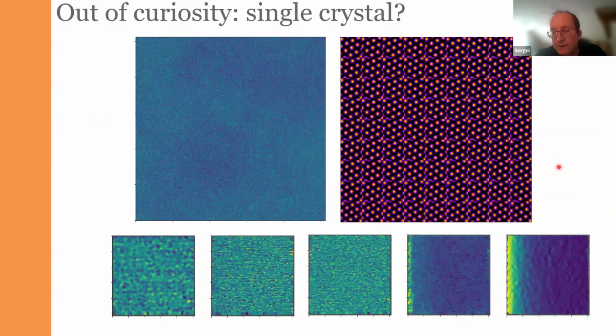Now, another very interesting thing that autoencoders allow us to do is that they give almost impossibly precise information about the uncontrollable factors of variation inside the material. What I mean by that is, if I take interesting looking images, meaning multiple phases, defects, whatever, VAEs are going to find those as the factors of variation. However, if I take the image of an ideal crystal, which doesn't show any factors of variation visible by eye, and I do the same analysis, then my VAE is going to identify the very small distortions that are associated with the imaging system.